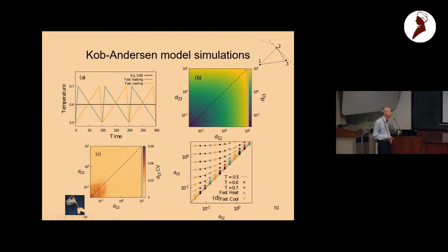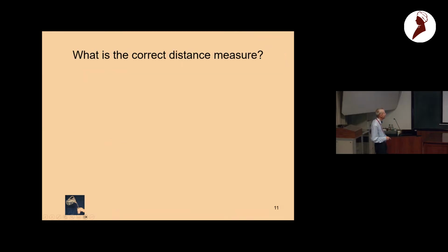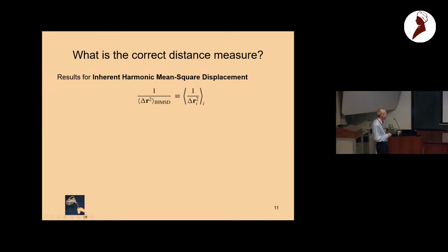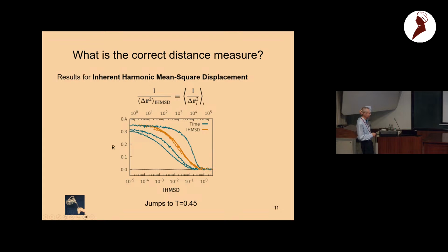It turns out that was not the correct distance measure to collapse all data, but it worked pretty well. And the question really is, what is the correct distance measure if the material time change is simply a function of how far we have moved? And we tried different things, and Camille Scalliet suggested to us, why don't you use the inherent harmonic mean? And the harmonic has nothing to do with vibrations. This just means the 1 over n sum is called the harmonic sum. So the charm with this equation is that it emphasizes the slowly moving particles between two states. If you have moved a little small distance, you have a large contribution. So the slow particles are the most important in this distance measure. And that's the one we found to be best to collapse our data.